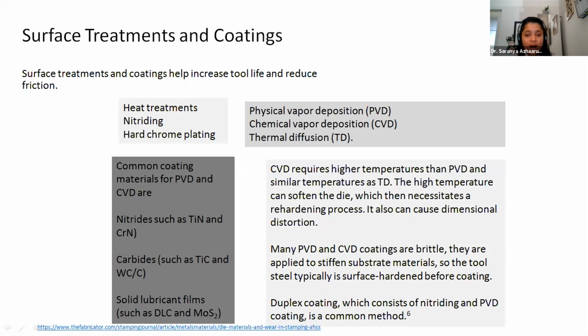And why is CVD different from PVD? Because CVD requires much higher temperatures than physical vapor deposition, and the high temperatures can really soften the die, which then again needs a rehardening process. So it can also cause some dimensional distortion. So there's a basic difference between CVD and PVD. And many PVD and CVD coatings are sometimes brittle because it's very thin, and it's very hard to make a hard coating with PVD and CVD.